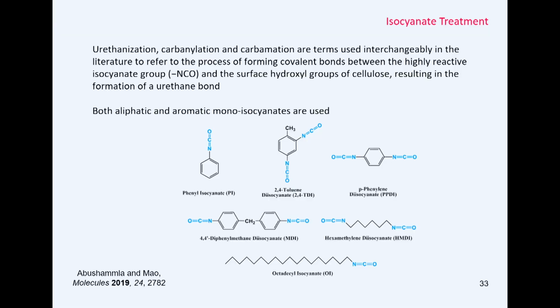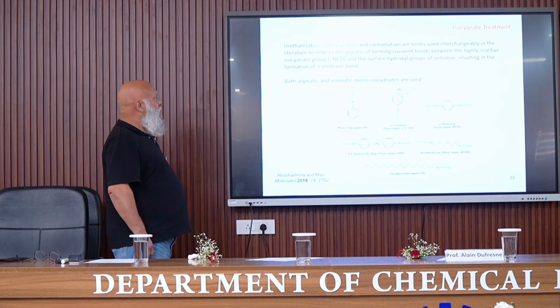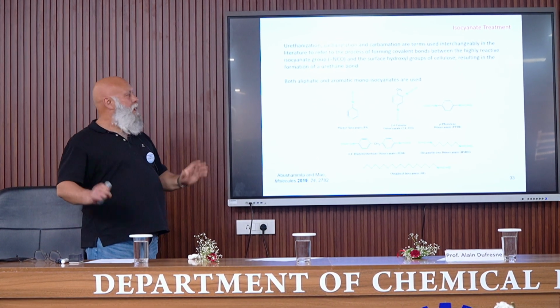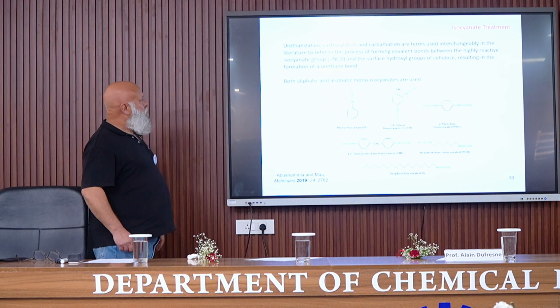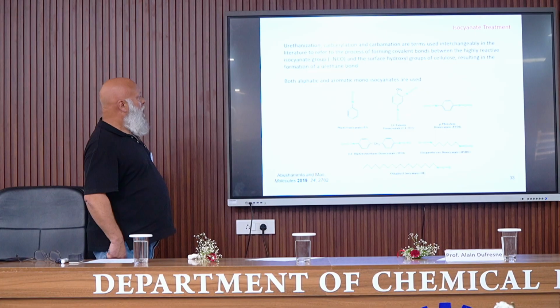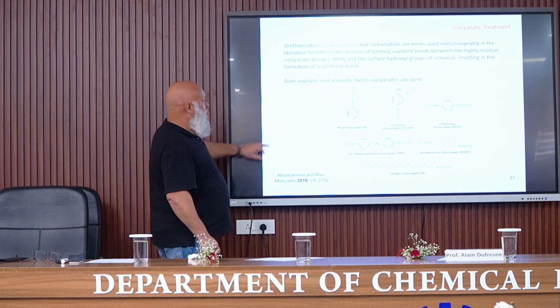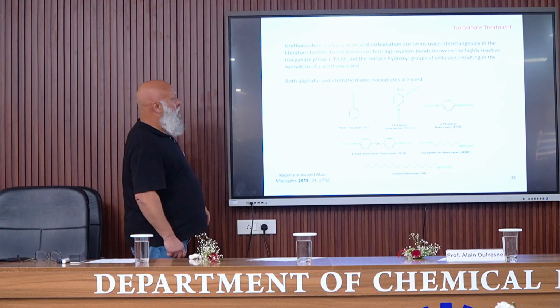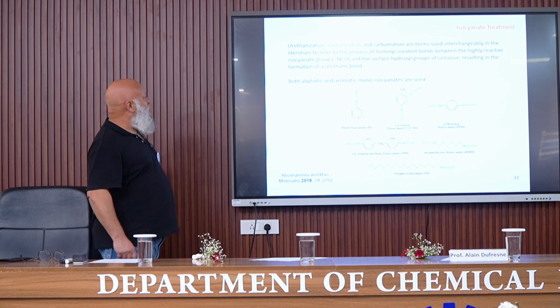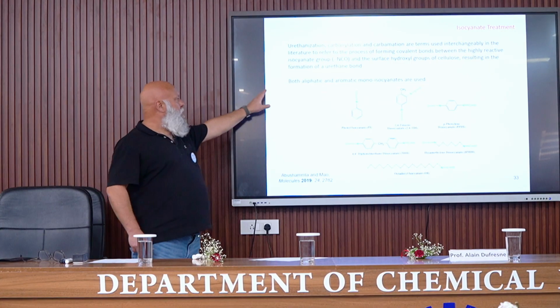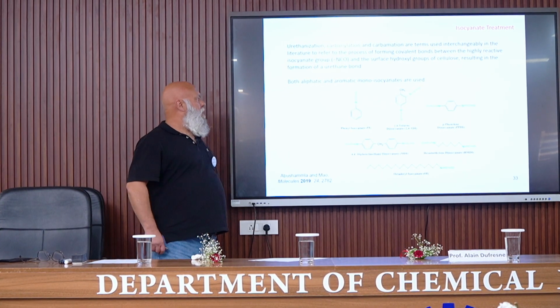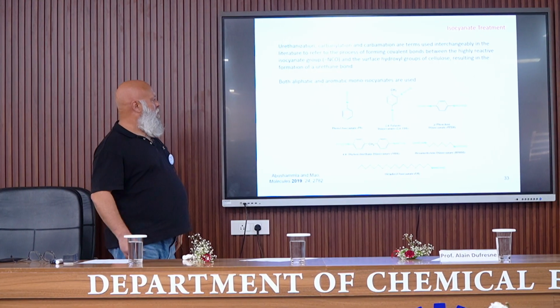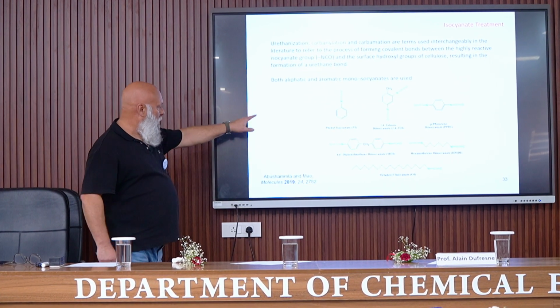So the same thing can be performed using isocyanate. So this kind of chemical reaction can be called urethanization, carbonylation, and carbamation, it seems. I'm not a chemist, but it can be used. And so the objective is to have some interactions between this isocyanate group and the OH group from the surface of the fibers. So it's possible to use aliphatic and aromatic monoisocyanate, but also diisocyanate. You have some examples here.